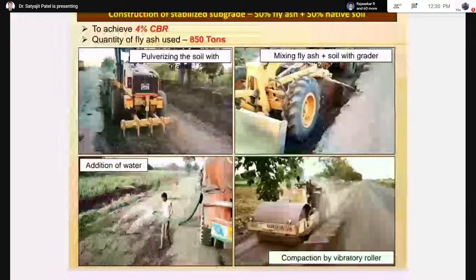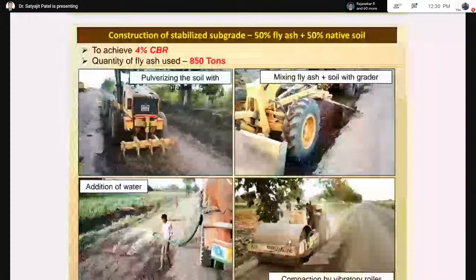So the soil of that road is black cotton soil, an expansive soil. The road has been designed for a CBR of 4%. The black cotton soil alone has a CBR of only around 1.5 or 2%, which has been improved by the addition of 50% fly ash, with 50% native soil taken in the subgrade layer, to obtain the designed CBR of 4%.